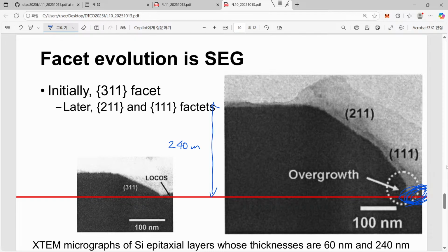So the growth of our silicon at this point is delayed. That's the reason why we have a certain slope here. However, away from this point by a certain amount, you can see that this growth is just planar, and you can find just the expected behavior of our one-dimensional planarized epitaxial growth.